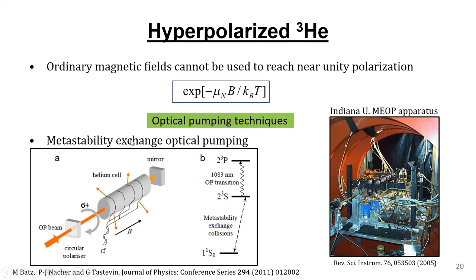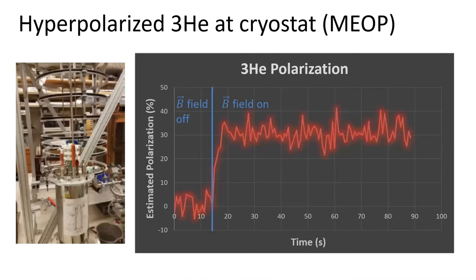In a tabletop version of their apparatus, they were able to get about 70% polarization in the past in a relatively short time scale, in the matter of only a few seconds. Very recently, they've implemented a miniaturized version of that polarization setup on top of a cryostat test assembly, where very recently now we've been able to show some first results on polarization, which is already at the 30% level, at the first turning on level.